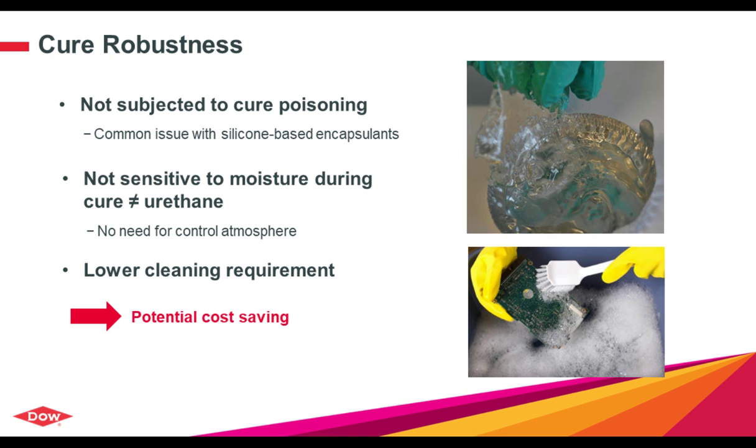When you are facing that, this is generally due to either solder flux of bad quality, or bad cleaning of the board, or cheap components that can have some volatiles in there, creating a lot of issues. With this chemistry, so far we have not seen any inhibition with all the different testing that we have done, with various applications and various customers as well. This has never been seen, like with the other chemistry, as we are talking about something completely different here.